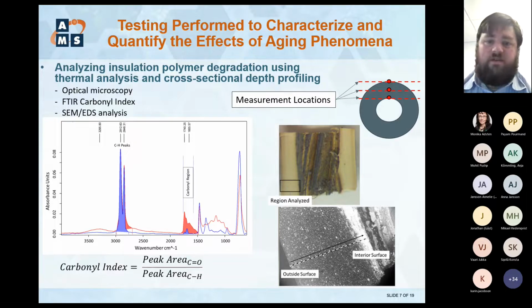We're looking at all kinds of different data to understand, okay, what does the material look like holistically? How is it aging? Is it inhomogeneous? Is it homogeneous? What kind of different effects are going on? The techniques we've used to look at these types of aging issues include optical microscopy, so just general visual inspections, trying to look at discoloration, carbonyl index using Fourier transform infrared spectroscopy, and then scanning electron microscopy with energy dispersive X-ray spectroscopy analysis. We're looking at distribution of different elements, oxygen, and in some cases copper if there are interactions, and I'll show some of those results in a second.